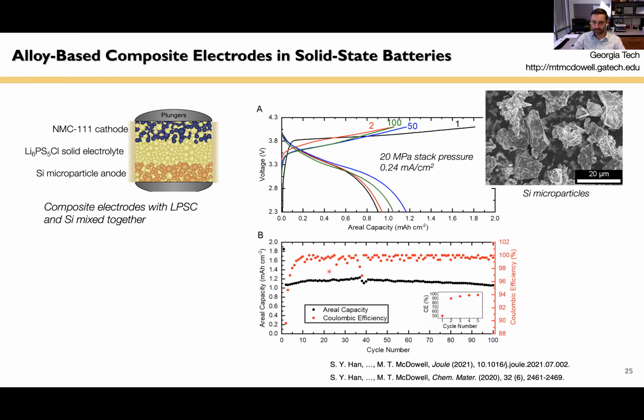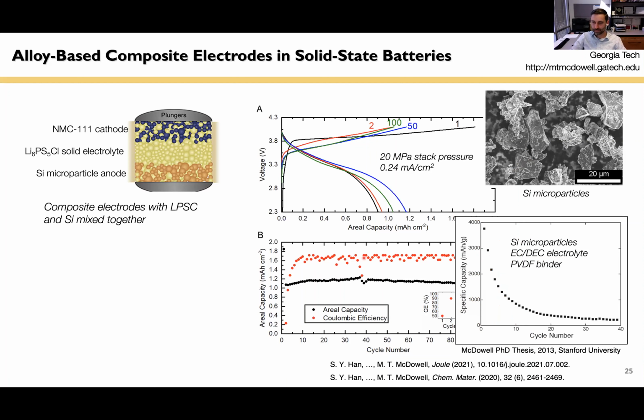So I think this is the really exciting part. We're showing that there is some promise here of using these microparticles. This is published here in this Joule paper from earlier this year. So if we compare this to how these similar particles behave in a liquid electrolyte battery, shown here, they rapidly decay, basically. And this is because of the volume changes and the SEI formation and all that I talked about already.